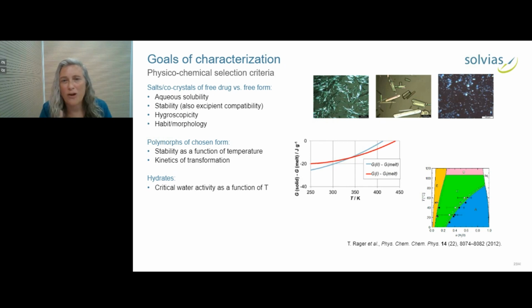And then as you increase the water activity, which also corresponds to increasing the relative humidity, form C, the dihydrate, becomes more stable. And finally, in this case, form A was a pentahydrate, was stable at room temperature from water activities of 0.4 to 1. So from 40% to 100% relative humidity, this was a stable form. And this had a large range and was chosen as the form for development.